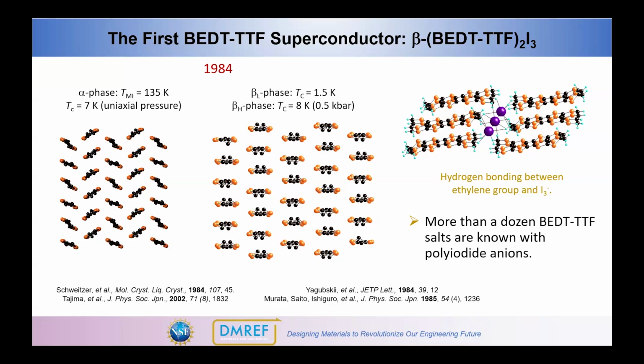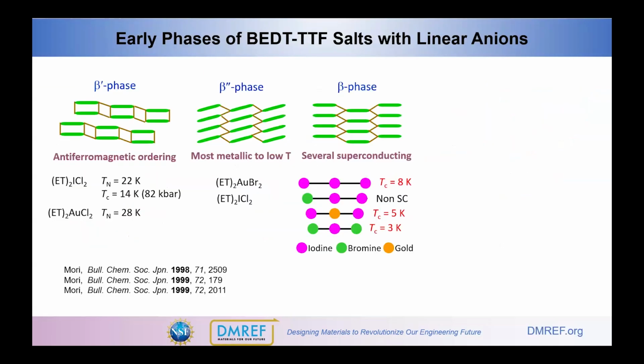And it was understood fairly early on that these hydrogen bonding interactions between the hydrogens on the ethylene groups and the I3 anion are important for various purposes. I'm not going to really go into the details of that now, but with respect to the orientation of the ethylene group and other things like that. And so now, I've probably lost count a little bit, but there are at least a dozen phases of BEDT-TTF salts known with polyiodide anions, because of all the different I3, I5, and various other combinations of iodide anions. So these form as various different phases.